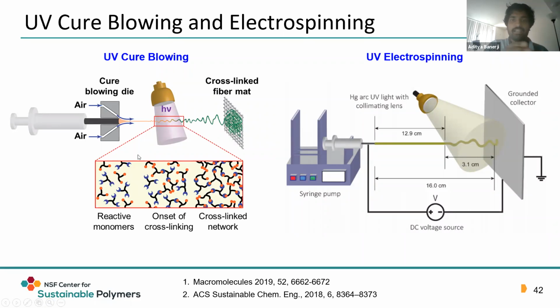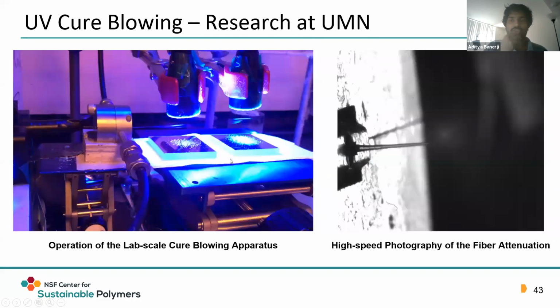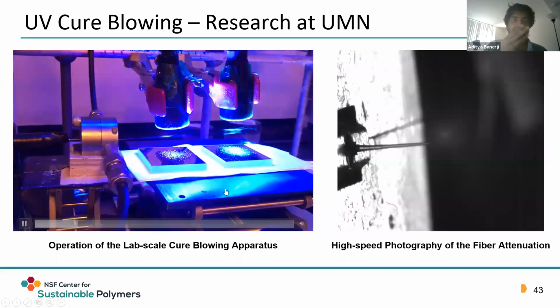And while in flight, upon shining UV light on them, there's a rapid cross-linking that occurs, which leads to formation of a cross-link network within the fiber mat, which is collected. So this also gives an additional benefit that you can get a cross-linked fiber mat at the end of this particular process. So in the next slide, I would just show a couple of videos which shows the UV cure